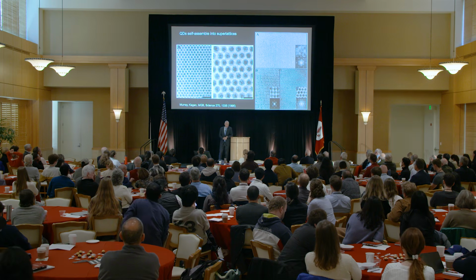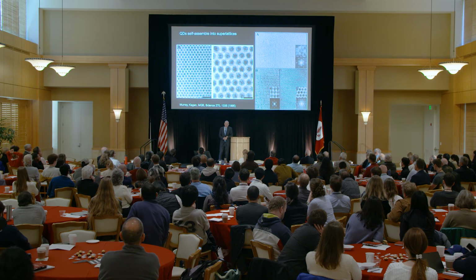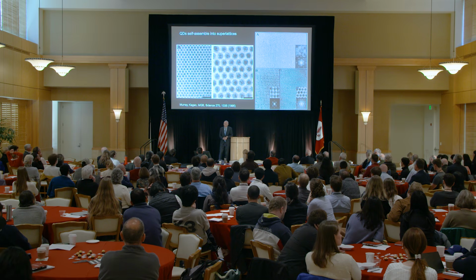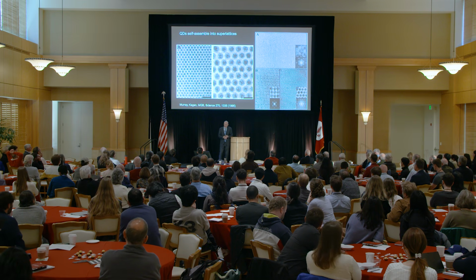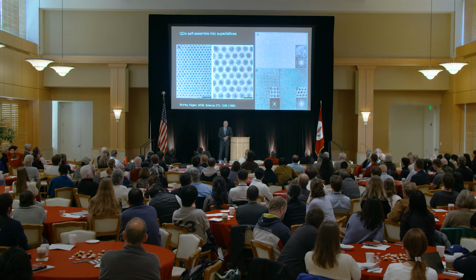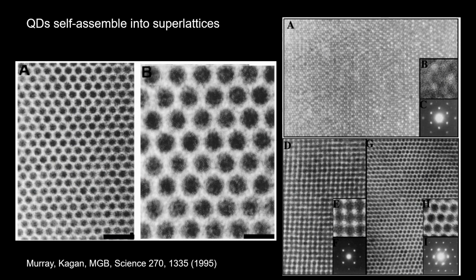So then that allowed us to do things that were kind of accidental, but these things ended up crystallizing as quantum dots, basically crystals of dots. And if you think of the dot as an artificial atom in some ways, then you're creating a lattice of artificial atoms where you can control the material. It doesn't have to be cadmium, it could be any other material with an energy that can go all the way from the UV into the infrared. And depending on how close they get together, they begin to talk to each other.